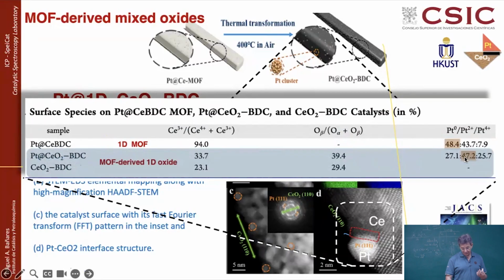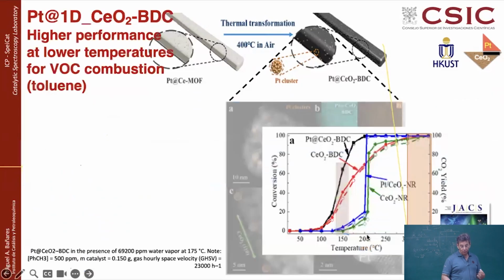oxidized than before. And in the case of cerium, of course, it was a ligand compound with a big fraction of cerium 3+, and now it has a lower fraction of 3+ and more 4+. So basically, this is the cerium oxide with some reduced sites. So you have burned away the organic ligands and you have a mixed porous oxide with big interfaces between platinum and cerium. And we are using this also for the combustion of toluene.